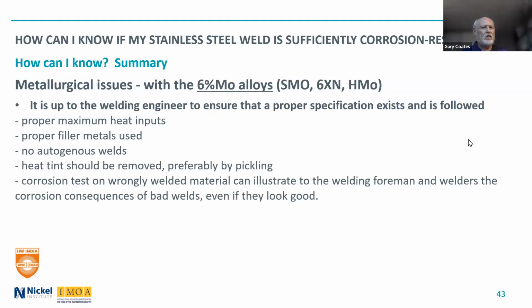With the 6% Mo alloys, it's really up to the welding engineer to ensure that a proper specification exists and it is followed. Maximum heat input, proper filler metals, no autogenous welds. Heat tint should be removed, preferably by pickling, because it gets the chromium depleted zone. Corrosion tests on wrongly welded material can illustrate to the welding foreman and welders the corrosion consequences.